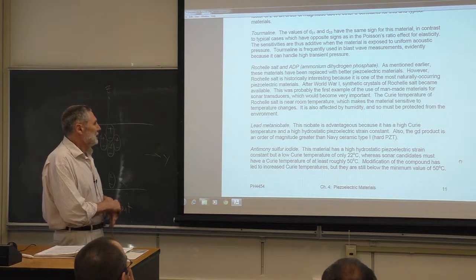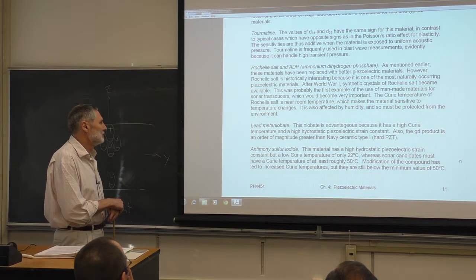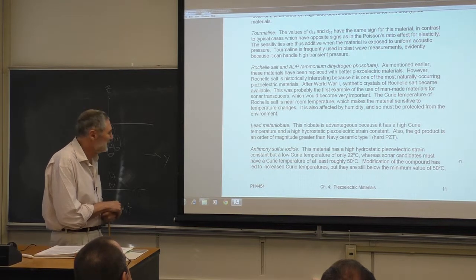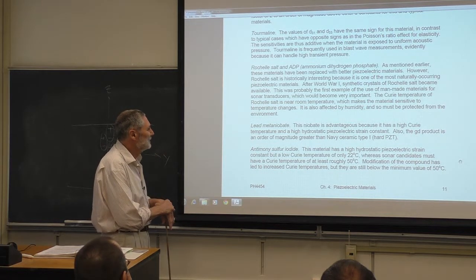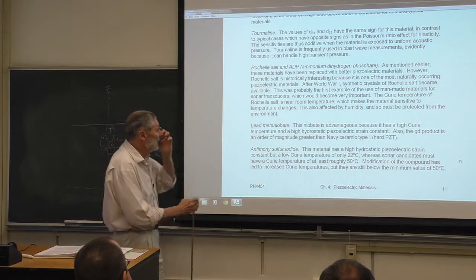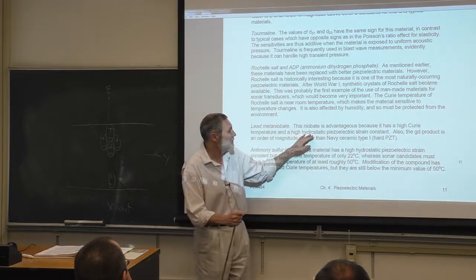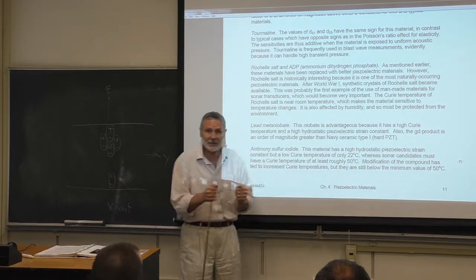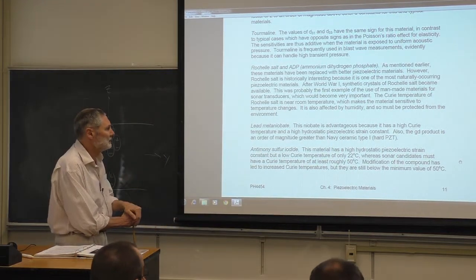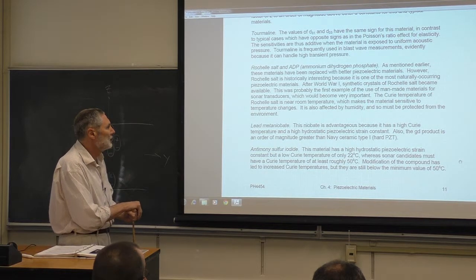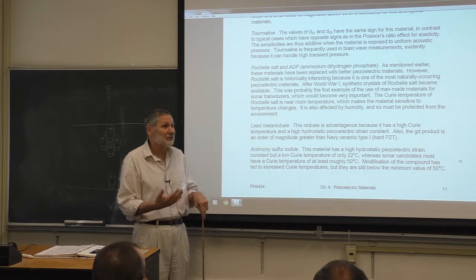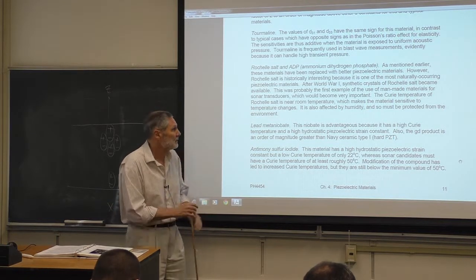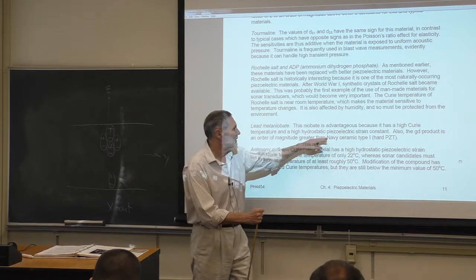Lead metaniobate has a high Curie temperature and a high hydrostatic piezoelectric strain constant, so you get a lot of transduction when subjected to hydrostatic pressure. And look at this: the G·D product — which is what you need if you're trying to pull a weak signal out for a hydrophone — is an order of magnitude greater than Navy type 1.